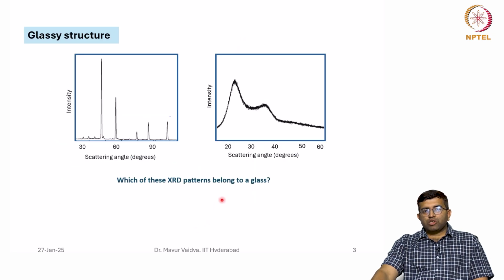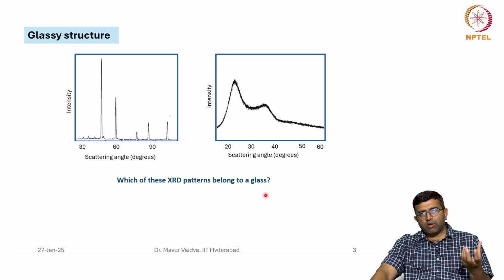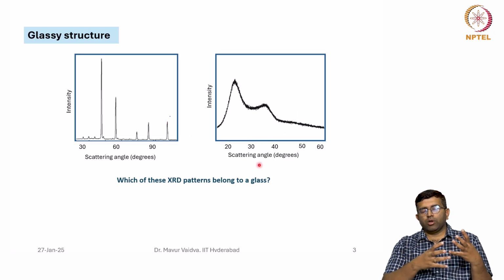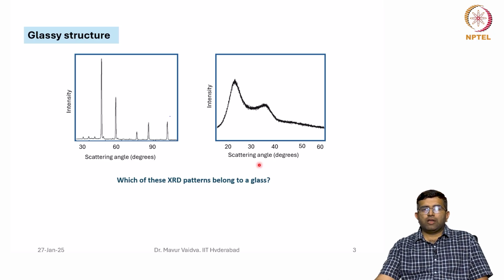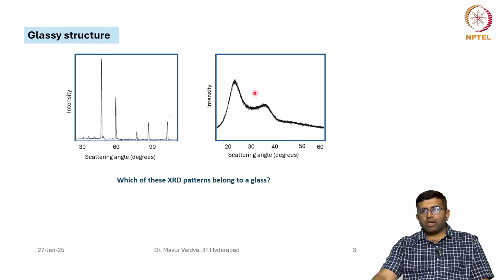So, if I have to ask you which of these patterns belong to a glass, as I said, it is the one that does not have a structure or a periodicity. This belongs to a typical crystalline alloy where there is translational periodicity, where there is symmetry, rotational symmetry also. So, this is an XRD pattern for such a crystal, whereas amorphous materials, as I said before, have a structure like a liquid, which is completely random and not periodic. Therefore, the diffraction pattern only shows a hump kind of a feature.